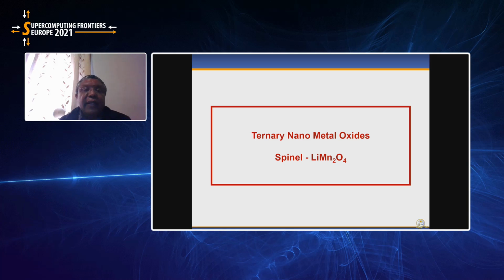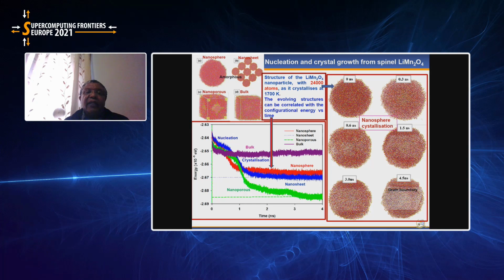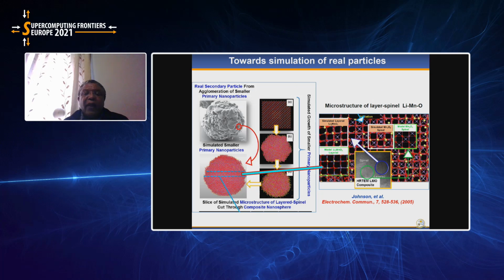Another important material is the spinel LiMn2O4, which is less costly and quite powerful. This has also been grown by amorphization and recrystallization. You have nucleation and crystallization of the materials. This represents just a primary particle in a secondary particle consisting of many primary particles. When you cut it in the middle, you get a microstructure which is composite. It has layered structures and spinel structures in it.